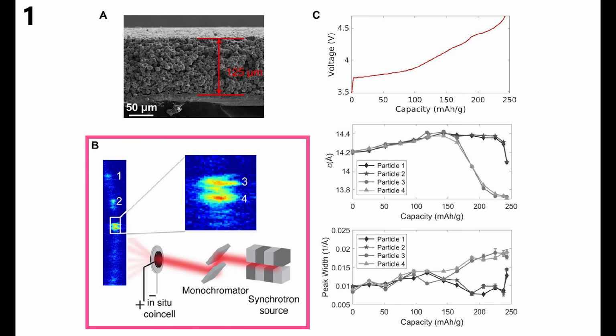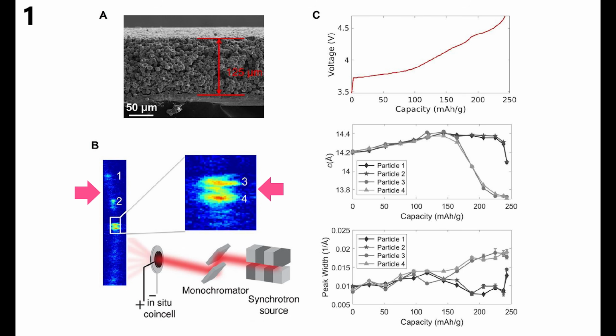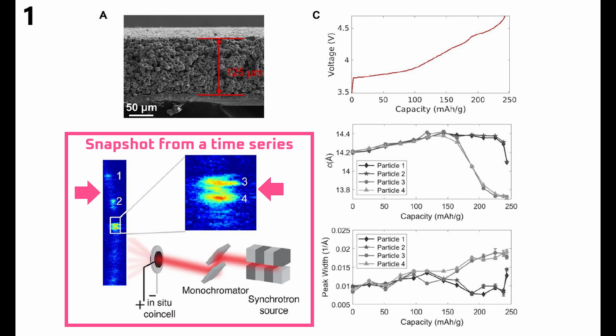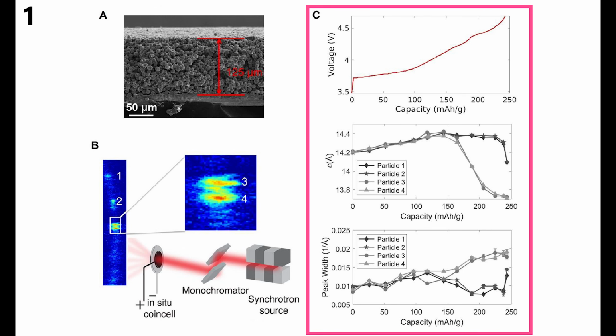Figure 1B shows a cross-section of that cathode using X-ray diffraction, and there are 4 spots highlighted and numbered, which are pinpointing specific cathode particles. The image is a point-in-time snapshot of a series that was captured using video, and the different colors indicate changes in the crystal structure that occur as lithium ions leave the cathode during charging. That time series data is graphed out in Figure 1C, where the progression of the crystal structure changes during charging can be seen more clearly.